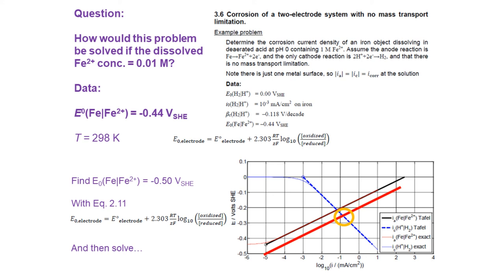The answer is that we would only adjust this slightly. Before we start, we need to calculate the actual equilibrium potential of the iron electrode. We need to know the temperature. We might be given the temperature, in this case 298 kelvins, and we would plug that into the Nernst equation to work out what the equilibrium potential of the iron reaction is at the real concentration of dissolved Fe2+ ions. And once we have that equilibrium potential, then we would plug that into the Tafel equation and solve exactly in the same way by saying that the anode current density is equal to the cathode current density. And if we did that graphically, we'd find out that the corrosion potential is a bit more negative, and the corrosion current density is a bit more positive.